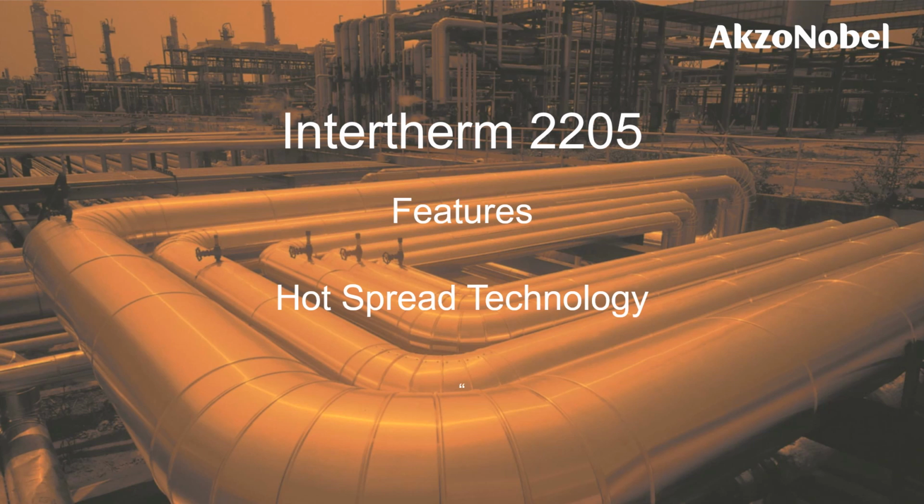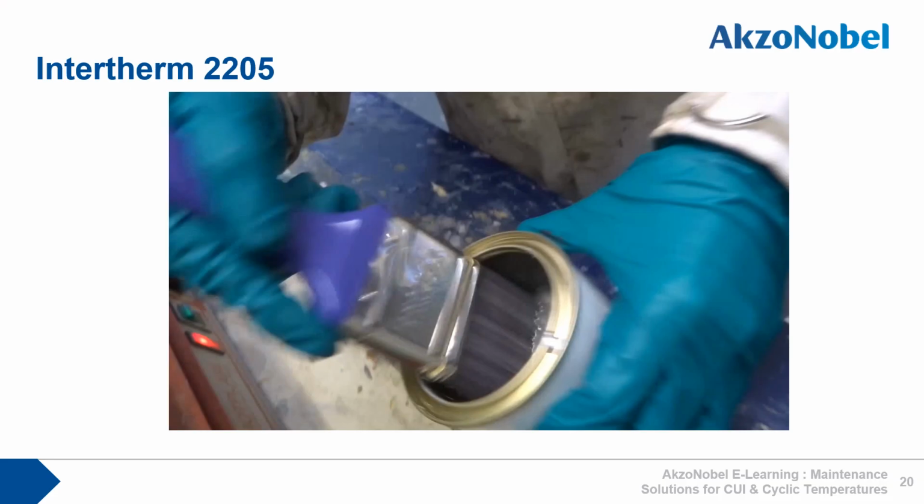Let's now look at some of Intertherm 2205's product features in more detail. Firstly, what is the benefit of hot spread technology? Here, Intertherm 2205 is applied to a hot panel at 150 degrees C. The first thing to note is how well the coating adheres to the brush, so enabling excellent transfer efficiency from can to substrate. Second, you can see how workable the coating is on the hot panel. This is its hot spread characteristic.